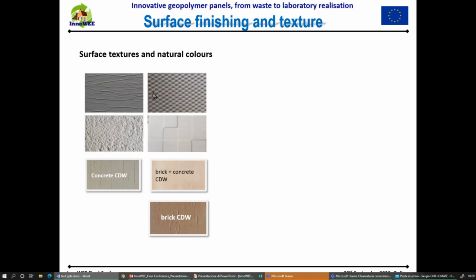It is easy to give the surface a particular design. The natural color of the geopolymer in our case is determined by the type of waste inserted: gray if concrete, red if brick are predominant. In our case, thanks to the other partner AMS, multifunctional color paints have been used that contain additives of a nanotechnology field that were used to enhance properties such as reduced water absorption, self cleaning, antibacterial, anti-mold, and thermal reflectivity.